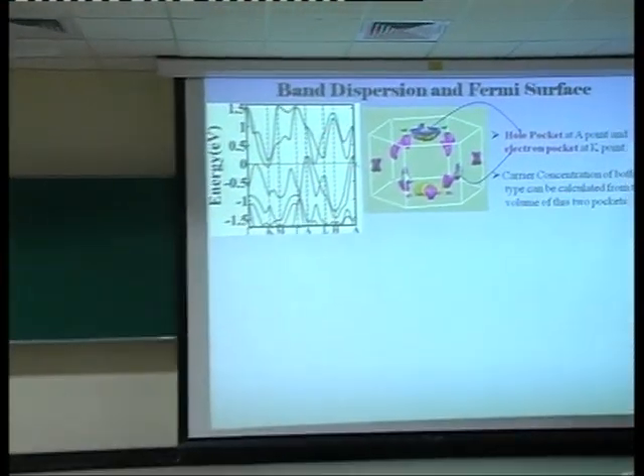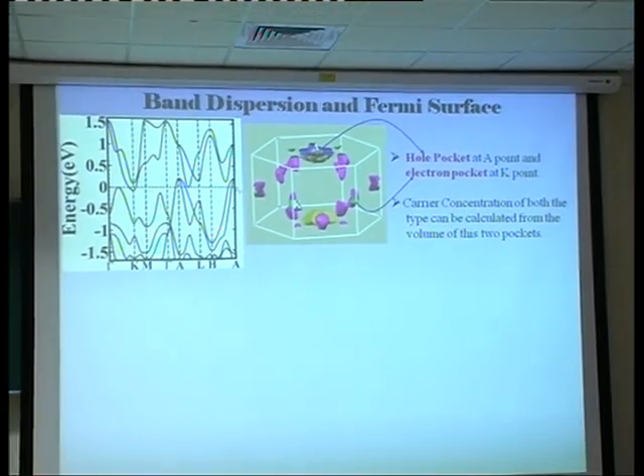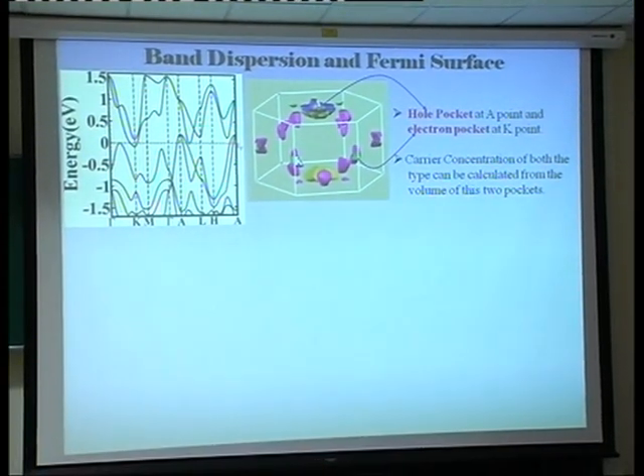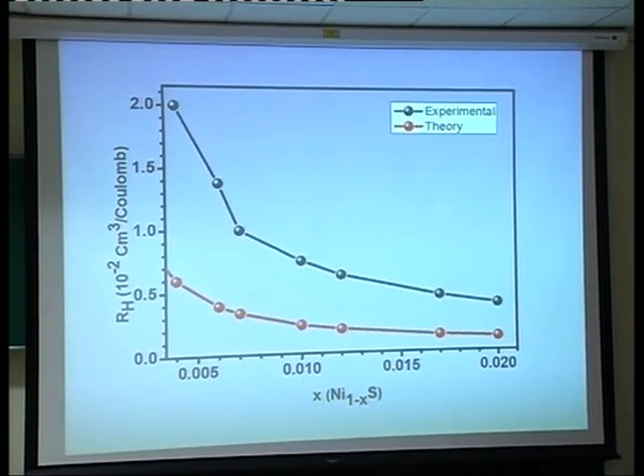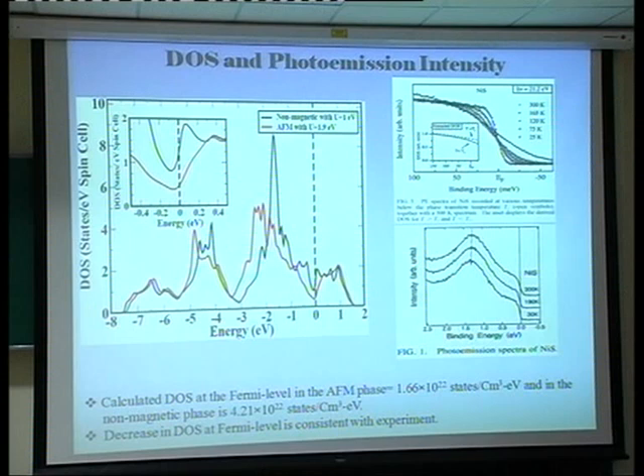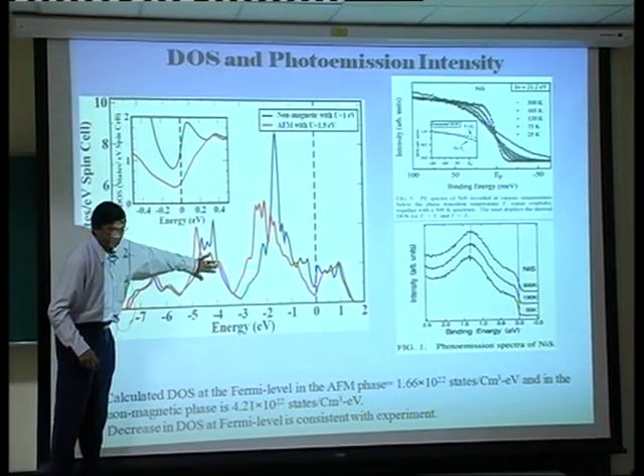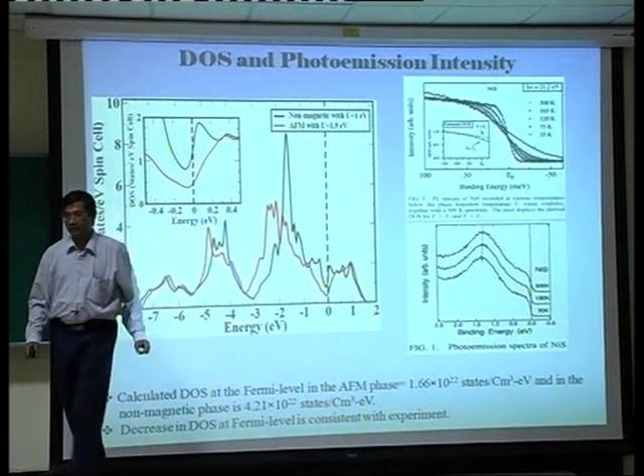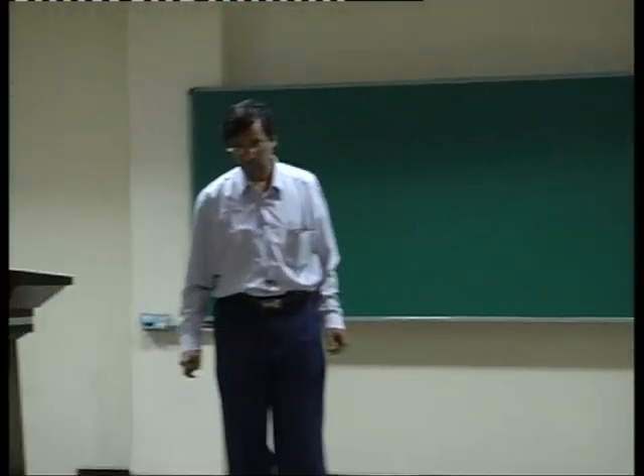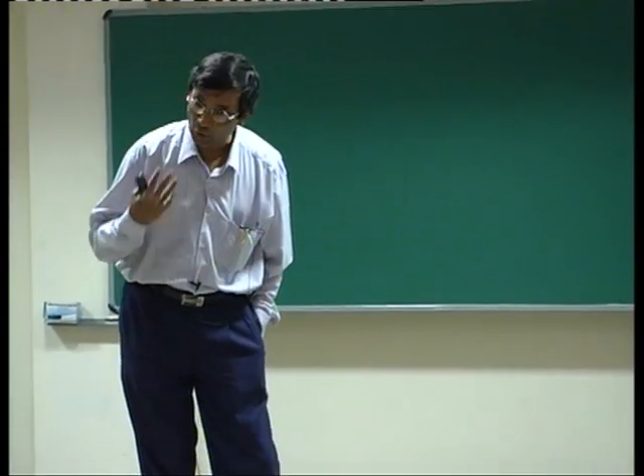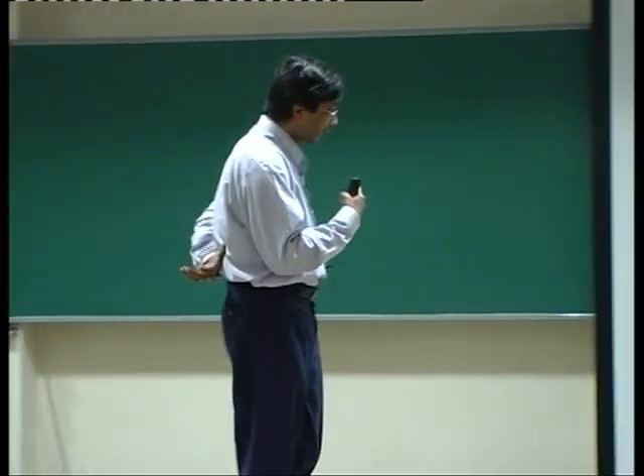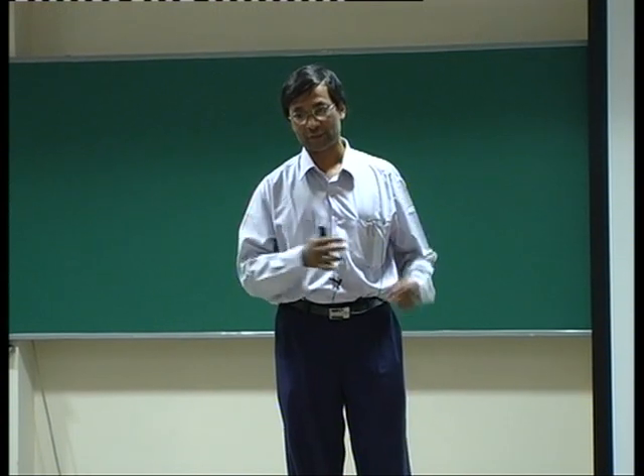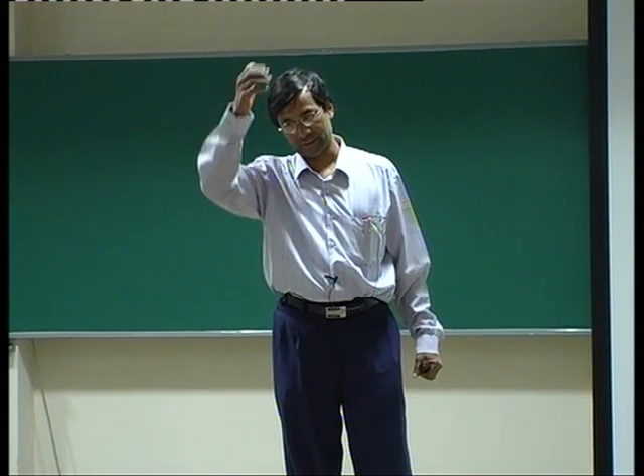Let me show. Remember the energy scale here, it's 1.5. If we analyze the data, it shows there's a lot of sulfur admixture, an enormous amount. But the nearest that I can show you to answer your question is the sulfur band here, and we have been looking at that. But when you say it's nickel-nickel self-doping, these also have a lot of sulfur character. These are dominantly nickel, but they have a lot of sulfur character. The other thing I did not mention is that we also understand the antiferromagnetic structure that's seen, ferromagnetic in the AB plane and antiferromagnetic along the C-axis. That comes essentially from the structural aspect.